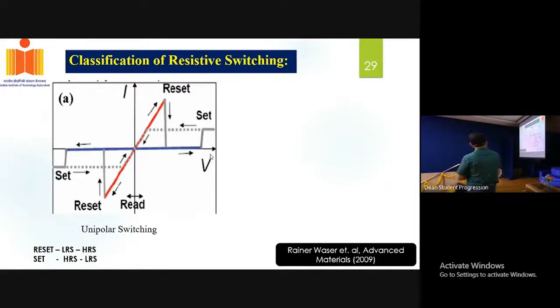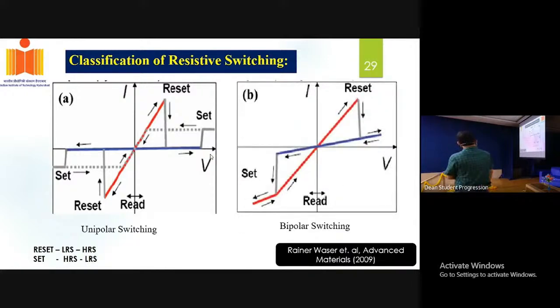As it is working on the principle of resistive switching, we can classify this RRAM in two different ways. One is unipolar resistive switching. If you can get the reset as well as the set switching with one polarity of the voltage, you call it unipolar resistive switching. And if you get the reset and the set switching, that is, from low resistance state to high resistance state and from high resistance state to low resistance state, with two different polarities, you call it bipolar resistive switching.